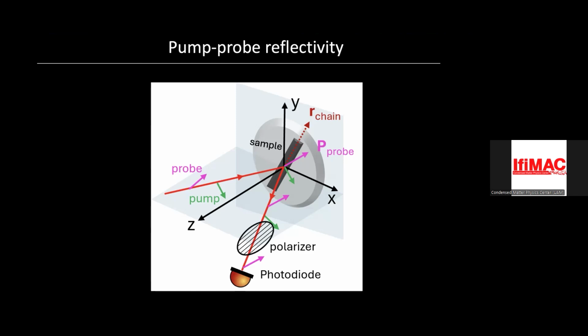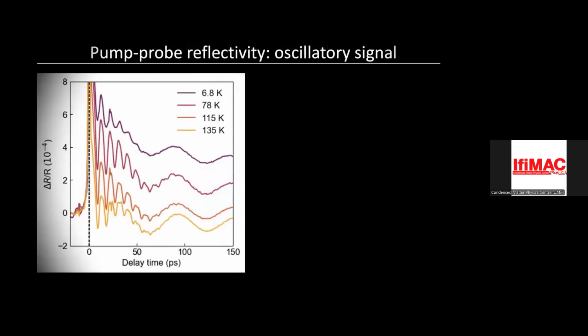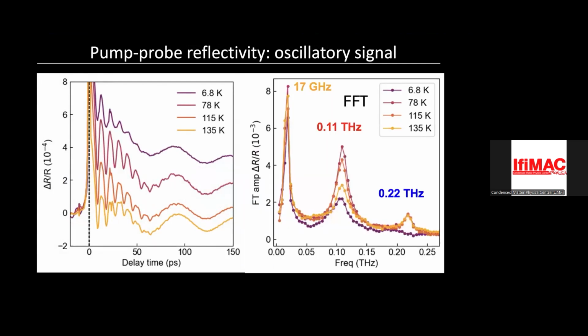We're able to basically take away the pump because they're differently polarized. So we have a polarizer that kills the pump and only sees the probe, and we measure the reflectivity of the probe. So we're doing a time-resolved reflectivity measurement, and this is our time-resolved reflectivity data. Again, you see lots of oscillations. Interestingly, you also see the slower oscillation, and that's the 17 gigahertz mode, which I'm not going to talk about today. But in this time-resolved reflectivity, you see two other modes, one at 0.11 terahertz, and the other, a much smaller one at 0.22. This intensity difference is telling you that this is probably just a second harmonic.